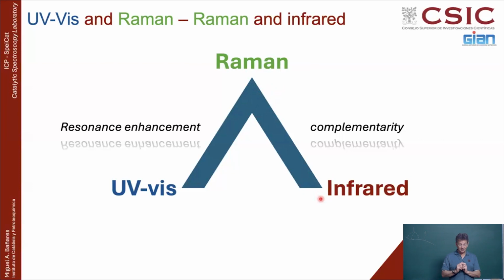Actually, you already knew that there was a complementarity, because the silica, the alumina, all these supports give very strong bands in infrared, and Raman does not. So you already knew that while they are reporting molecular things, they are looking at different things. They have different sensitivities. The other technique which is important is UV-Vis. UV-Vis is important because we make Raman with visible light. And it's not the same to use visible light, which is a laser, of a wavelength that has no particular interaction with your sample, than using a laser at a wavelength where your sample is absorbing. Because if your sample is absorbing that wavelength and you make a Raman with a laser of that wavelength, wow, there is resonance. And then you are triggering the signal. That is very nice. Oh, I didn't know. Then you get fooled, because sometimes you get something and the spectrum is dominated because a small component is absorbing.